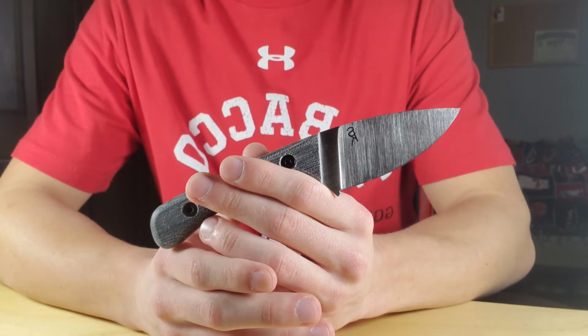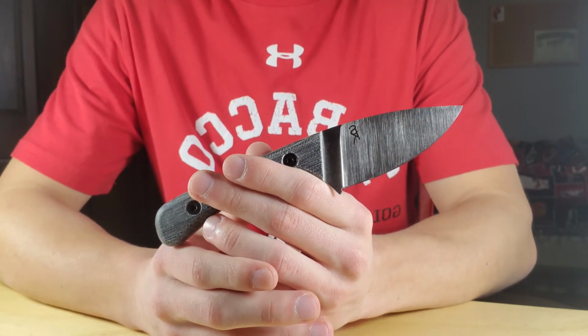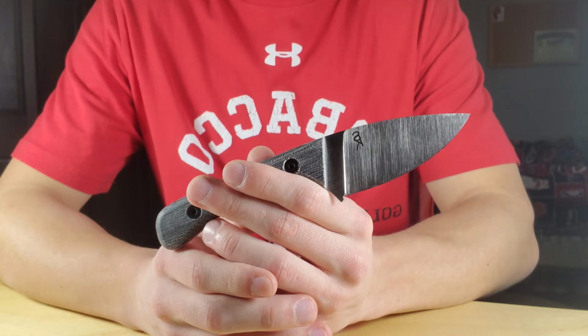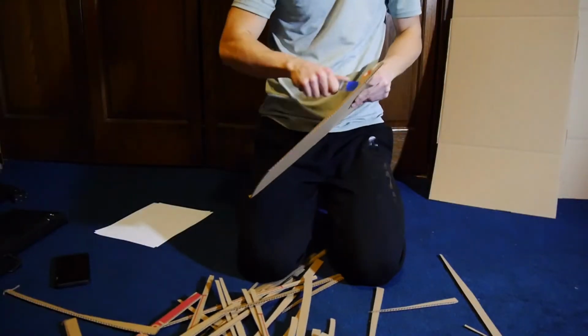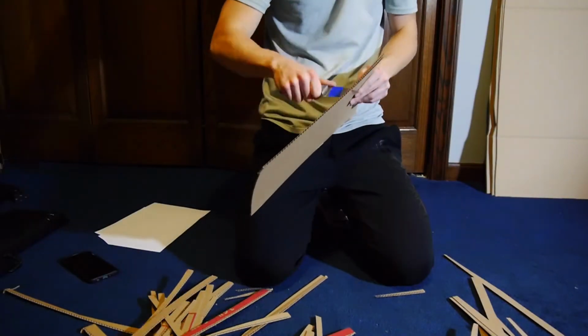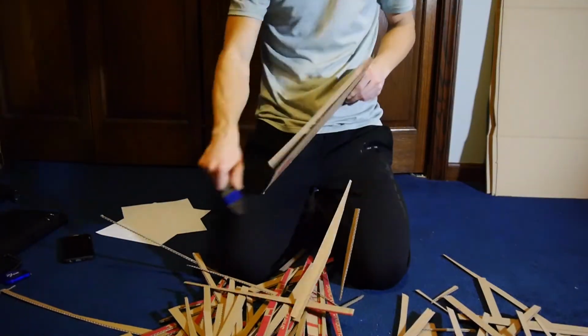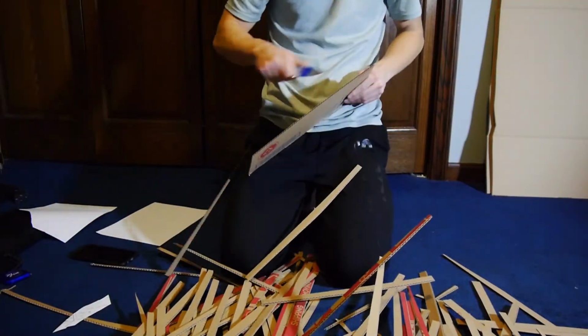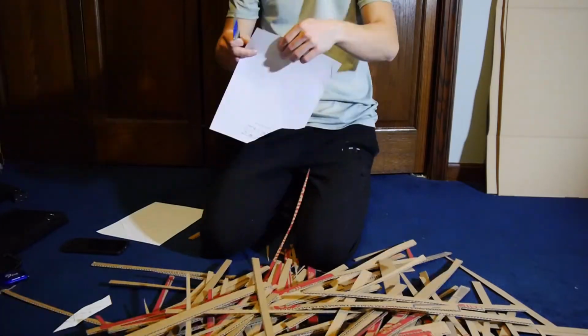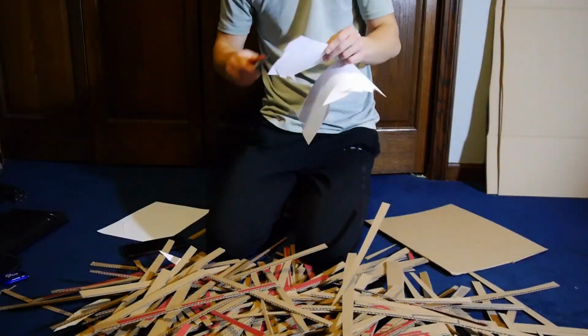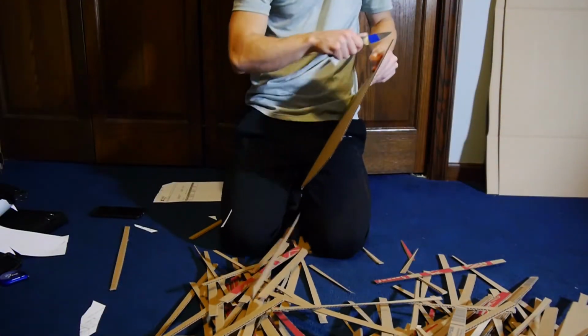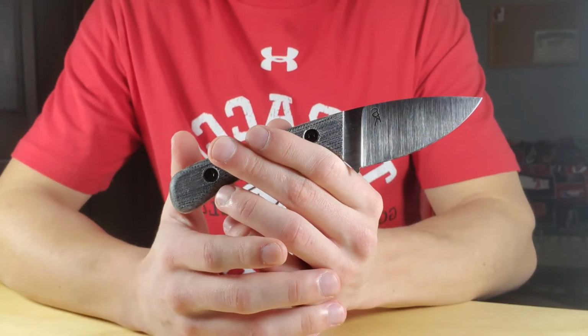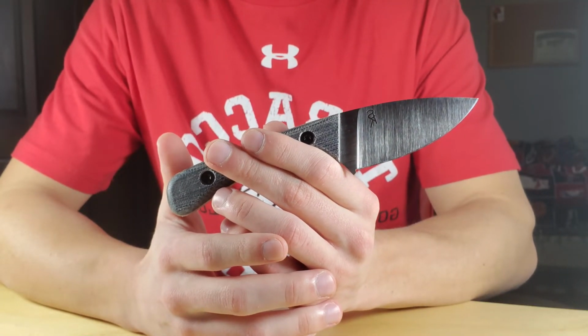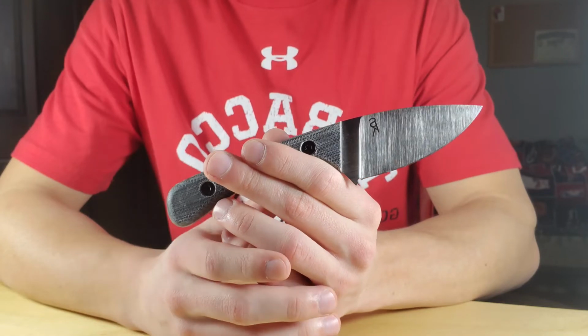So I went ahead and cut cardboard with this until it would no longer cut computer paper, and I've never really tested this one before. I just used it at work, used it at home whenever I get a chance if I need to do some extended cutting, because it's super comfortable and easy to cut with because of the thin stock and the thin behind the edge thickness. But this one ended up cutting 549.94 feet, which is the second best result ever, and the third result that we've ever had crack 500 feet.